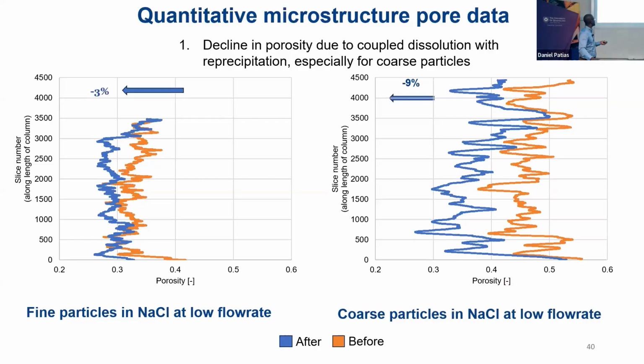Quantitatively, if you form precipitates, this is what we observe from that segmentation analysis. If you take your fines in sodium chloride rich brine, we realize there is less pore decline due to dissolution and precipitation, whereas the coarse materials result in a higher amount of decline. So about 9% for your coarse material, with porosity around 0.5 to 0.55 declining to 0.45 or 0.3 in some instances, whereas you don't see much here for the fines.